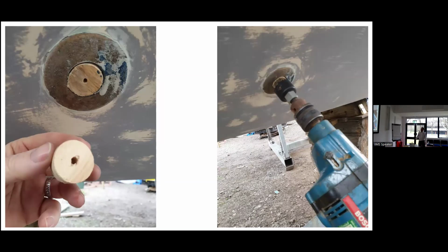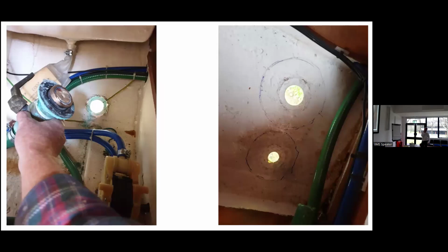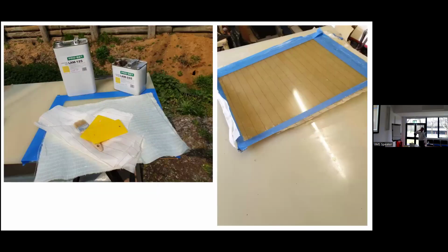Then I found that the hull in various areas was of weird thicknesses. I don't know whether this had been started on Friday and finished after a bank holiday weekend. I really don't know, but there were different thicknesses in areas of the hull that I didn't think were appropriate. Very thin in areas around the heads, and really thick around the waist. So on the next slide, you can see I made up some flat plate of epoxy glass with our laminating product. I actually used some unidirectional fabric that was from another project, stuff that I'd already got.